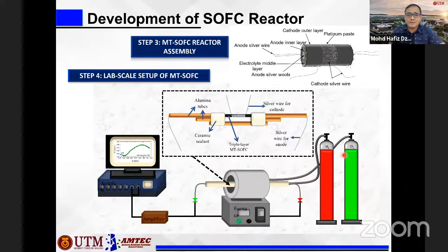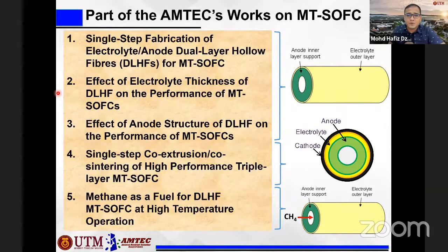So in AMTEC, this is some of the evolution that we have done in research on solid oxide fuel cells. We started with phase 1 to 3 on the dual layer hollow fiber membrane, and in phase 4 we moved to the triple layer hollow fiber membrane, and in phase 5 we tried to use methane as the fuel. For the first 4 we used hydrogen only, but for the last one we tried to use methane to prove that the microtubular solid oxide fuel cell can also use hydrocarbon fuel.